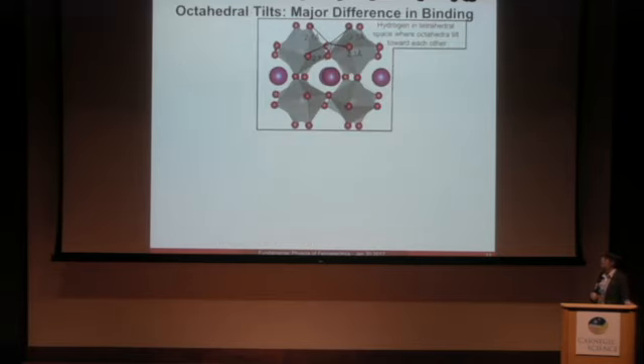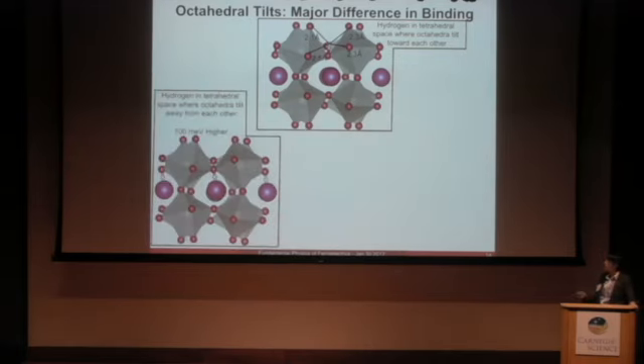So going towards adding explicit hydrogen into this structure. Because of the octahedral tilts present in the PBNM or P21/N structure, where you put the hydrogen really makes a difference. So here I'm showing you the low energy structure of the hydrogen. You see that it likes to sit in a tetrahedral space where the octahedra cant towards each other. If we compare this to just simply moving the hydrogen below to the tetrahedral space where the octahedra are now canted away from each other, we see that this is already 100 meV higher in energy.